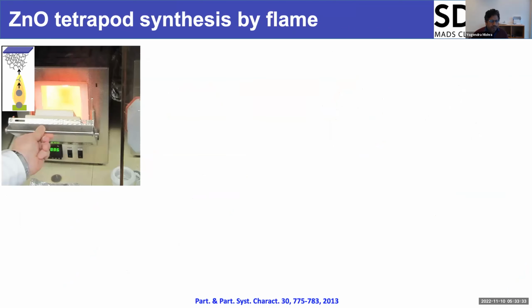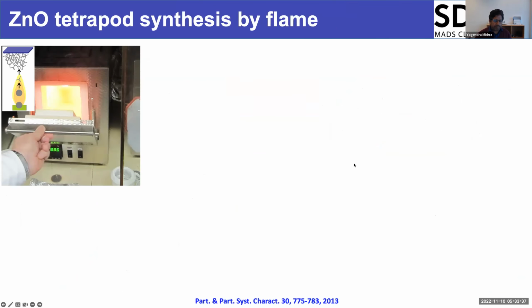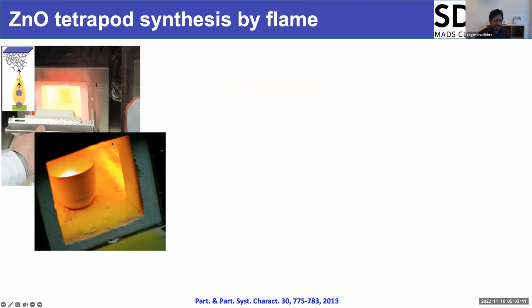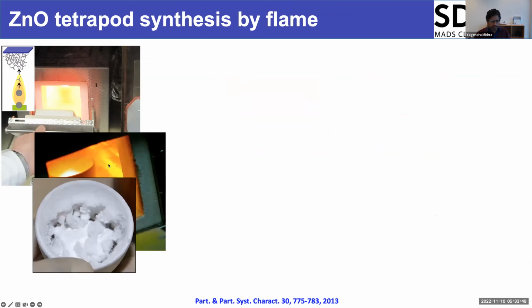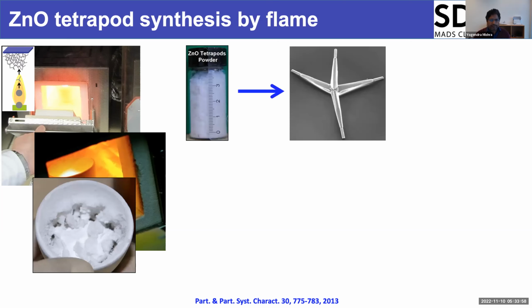And this is the process here: zinc oxide, you can see when the process is going on, the crucible is mounted into the oven at high temperature. And this is how the crucible looks when the growth is happening. The vapor you see is basically zinc oxide vapor. And after the process is over, we have growth. The white powder you see is micro and nanoscale tetrapods. We carefully harvest them and use them in desired applications.